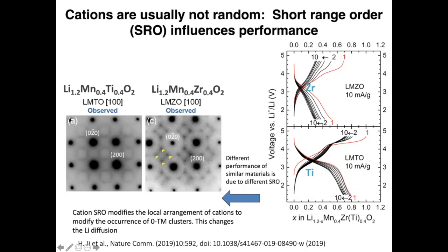And all we do here is we change the inactive element, the titanium, to zirconium. And we actually thought that would make a better diffuser because zirconium is bigger. But what you actually see is the opposite. If you look at the performance, the zirconate is actually very poor performance. The lithium manganese titanate, you can cycle about 80% of lithium per formula unit, again, up to 200 milliamperes per gram. And what we now know is that this is actually due to the short range order.